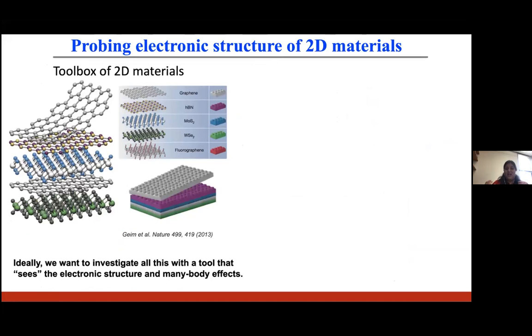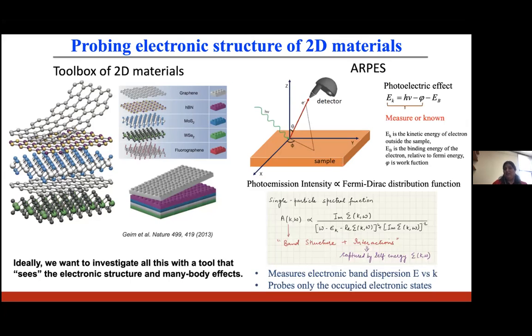And so now the question is, can we investigate these 2D materials and their heterostructures with a tool that can directly see the electronic structure and the many body effects in them without any assumption? And it turns out that we know ARPES, it's a powerful technique which we can use to directly probe the occupied electronic states by measuring the dispersion of the material. This technique is based on the photoelectric effect, where if we shine the sample with a photon beam, then electrons are ejected out, and the kinetic energy of these ejected electrons is given by this equation, where EB is the binding energy and phi is the work function. And so in ARPES, both the emission angle and the kinetic energy of the escaping electron are measured, and from there we can obtain the band structure.